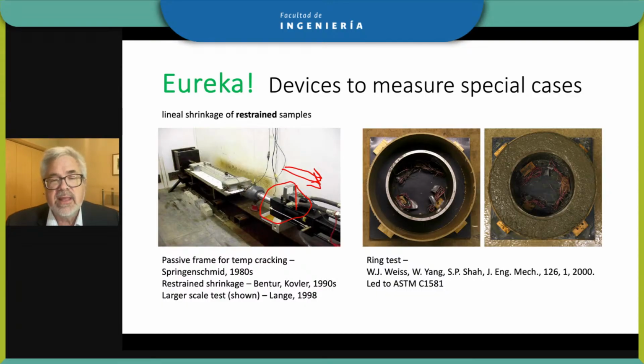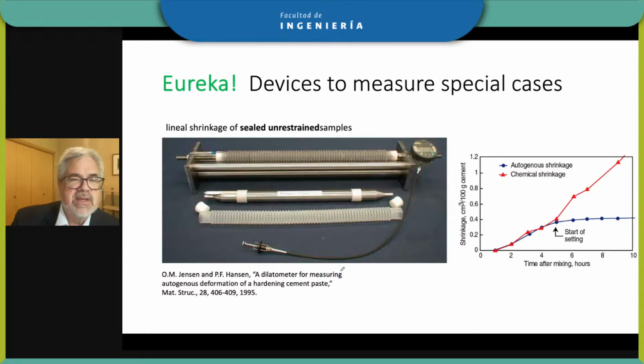And we also can more easily make a ring around a steel. This is steel in here. So the concrete goes in this area and the steel ring restrains it. And believe it or not, these strain gauges mounted on the inside of the steel ring will actually reflect the stresses caused by that shrinking concrete material. And then if it cracks, say in here, that breaks, and all of a sudden these strain gauges will read 0. They all get relieved instantaneously when that crack occurs. So these devices are in the literature in the 90s and 2000s as different ways to understand residual stress, restrained shrinkage.